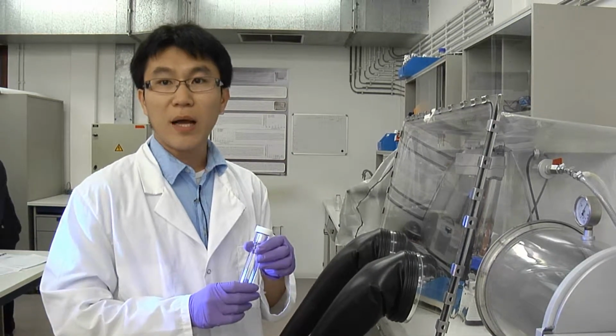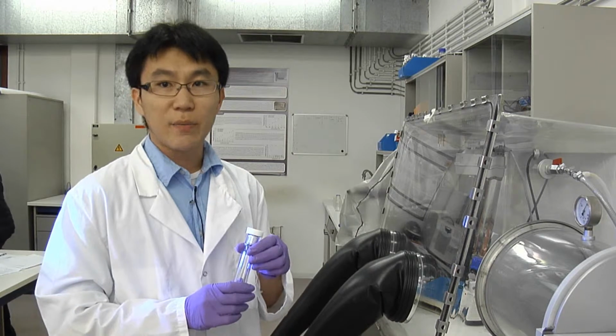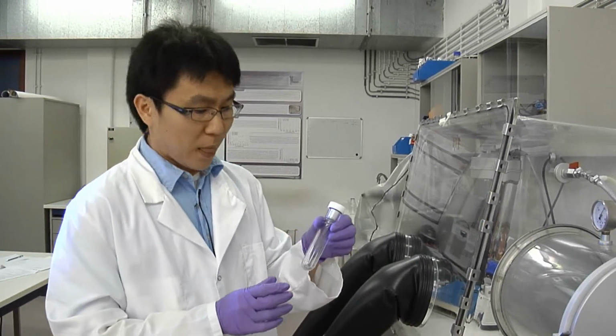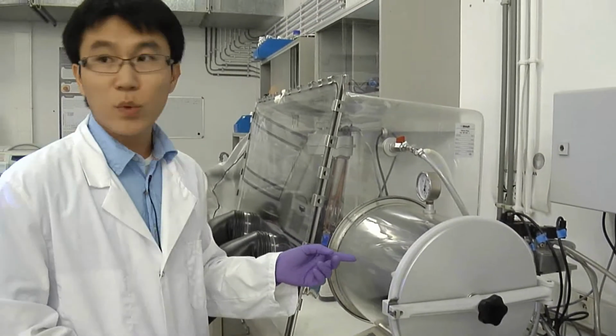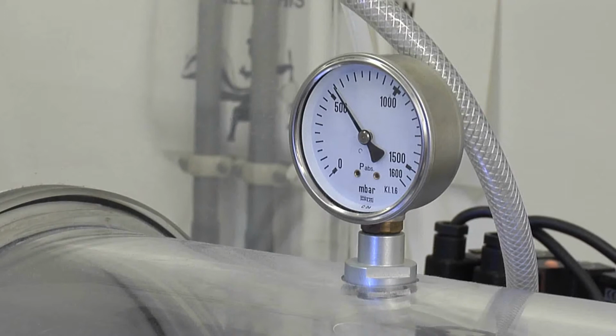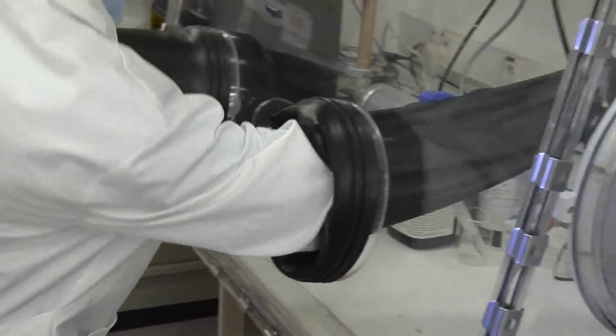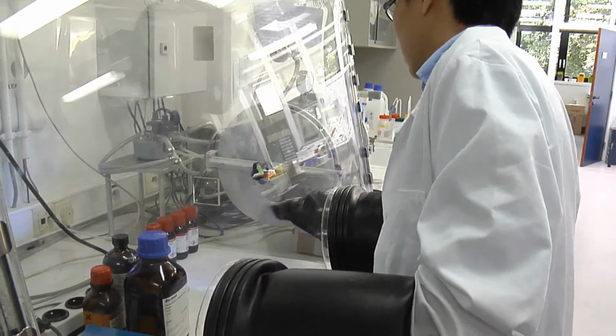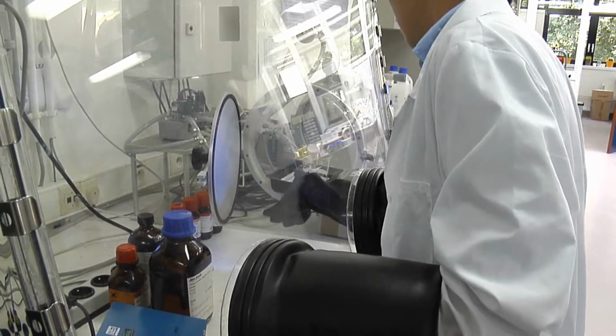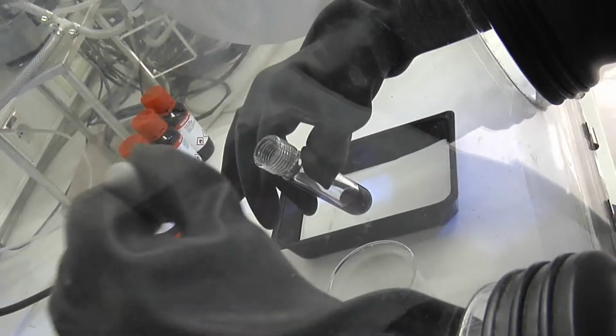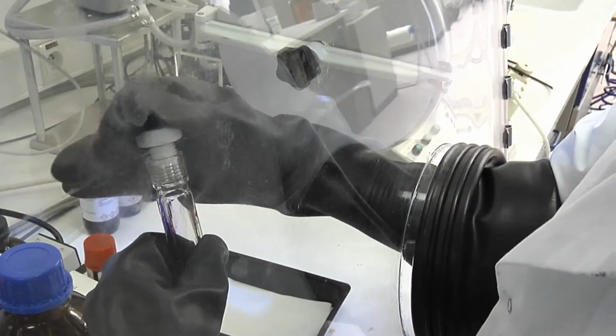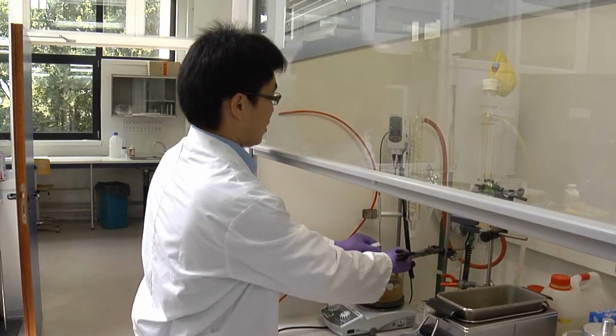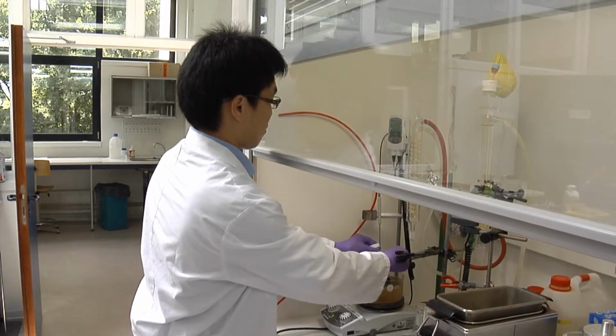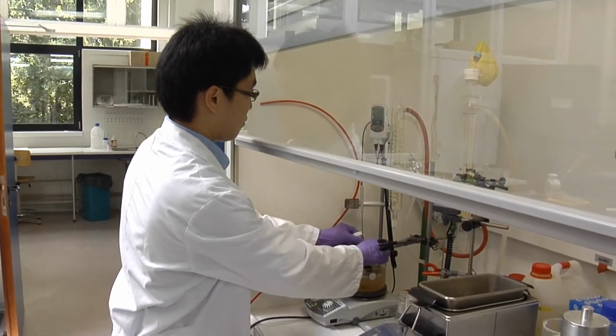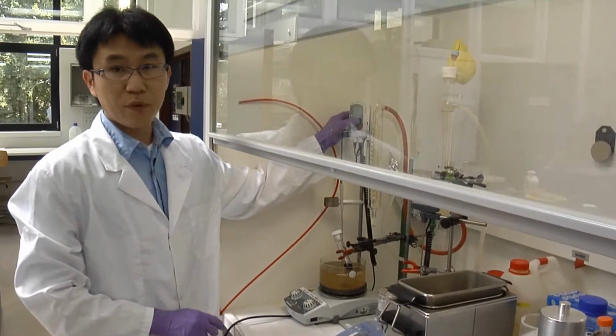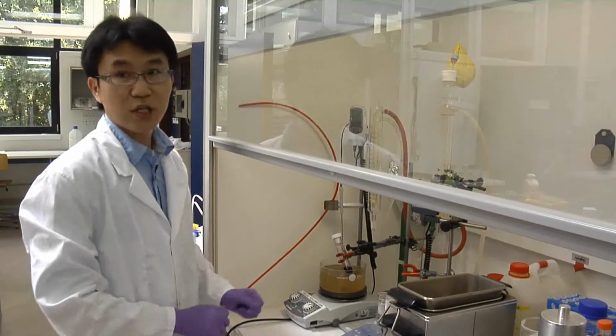The molecular dyes can now be coupled to the aryl boronic ester functionalized diamond through Suzuki cross-coupling reactions. In this transferring chamber, the flask will be vacuumed and purged with nitrogen gas. Inside the oil bath, after setting the correct temperature, I will start the reaction for 18 hours.